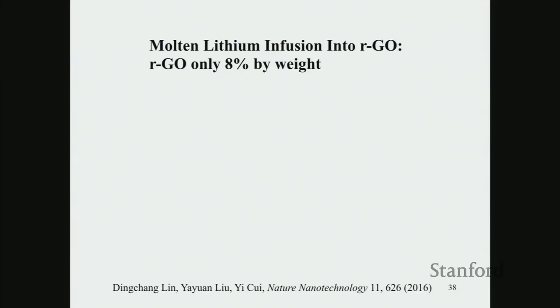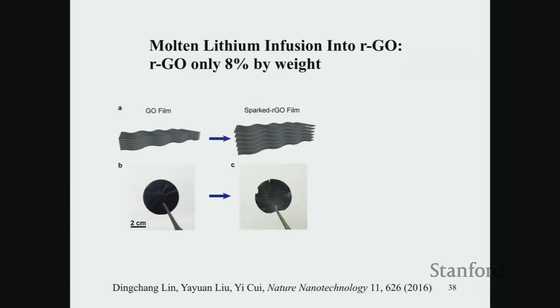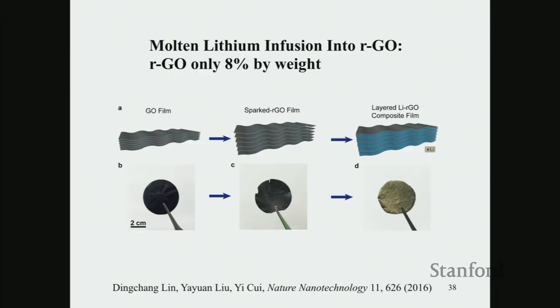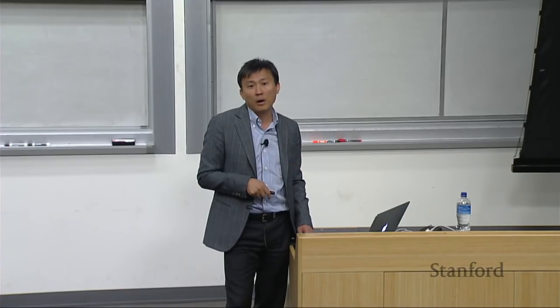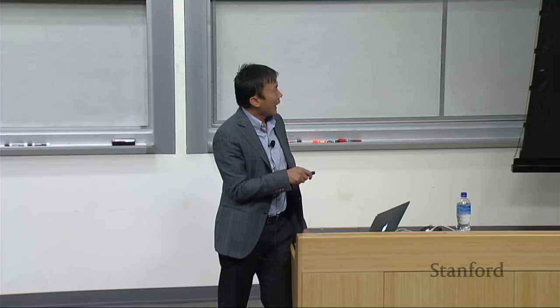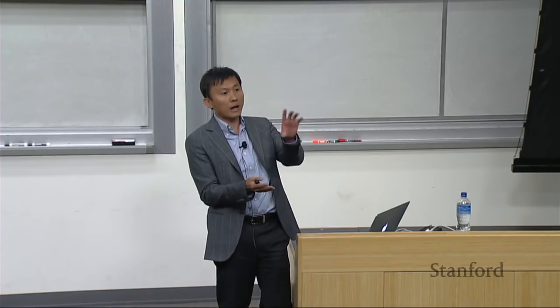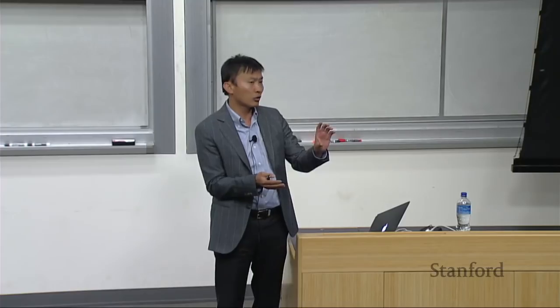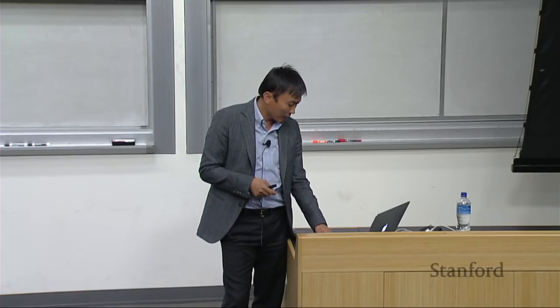We reduce graphene oxide, 8% by weight only, stacking into a layer structure by a filtration process, and put it into molten lithium. The molten lithium reacts with graphene oxide and generates a little bit of hydrogen bubble. Right, this will open the spacing between the gap, and the wetting happens. The molten lithium will wet into the graphene oxide and hide now between the two graphene oxide layers.